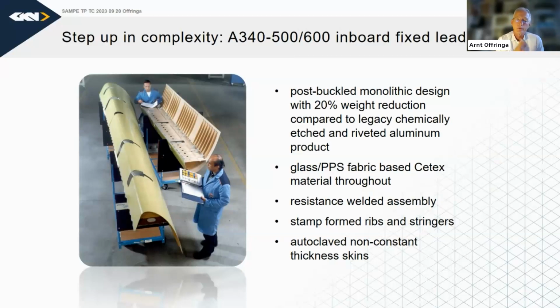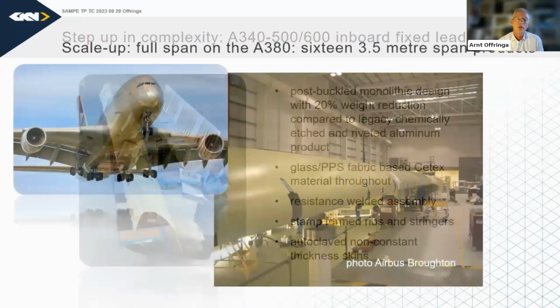So collaboration between Toray, ourselves, and Airbus resulted in this product, which is a welded structure with stamp-formed ribs, stamp-formed stringers, so stiffening elements. However, the skins themselves had to be autoclaved. We were hoping to make them out of autoclave with purely vacuum in an oven. But because of all the thickness variation in the product, the complexity of the layup, that proved to be a big challenge. So we did go to an autoclave.